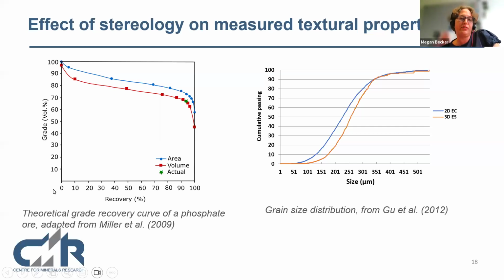So this, again, is the theoretical grade recovery curve. This comes from a study that Jan Miller had done on a phosphate ore. And he measured the theoretical grade recovery curve with tomography-based measurement. So the red is a 3D volume-based measurement, and the blue is a two-dimensional, area-based measurement from something like an MLA, QEMSCAN, or TIMA. So you can see that the area measurement is suggesting the material's finer, and actually the actual performance of this concentrator sat exactly on the curve. So in the case here, there was no further room for improvement for that concentrator. And if they had gone by the blue, they might have been trying to reach something that was unobtainable.